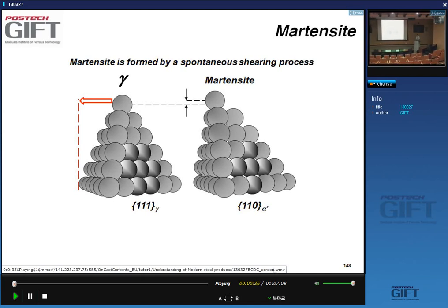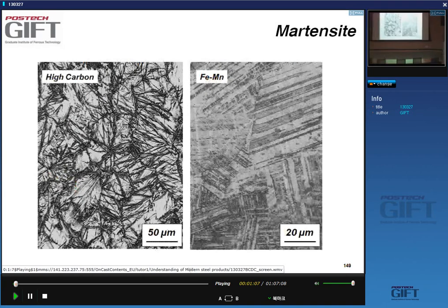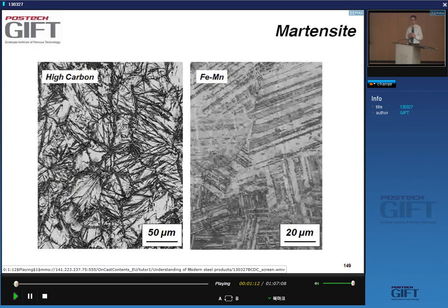And we can also see on the same slide that for that specific shear, certain gamma 111 planes are transformed to 110 planes of martensite very nicely. Okay, so there will be orientation relationships between the parent phase, the austenite phase, and the product phase, the martensite. All right. Again, I want to point out that for many steels,